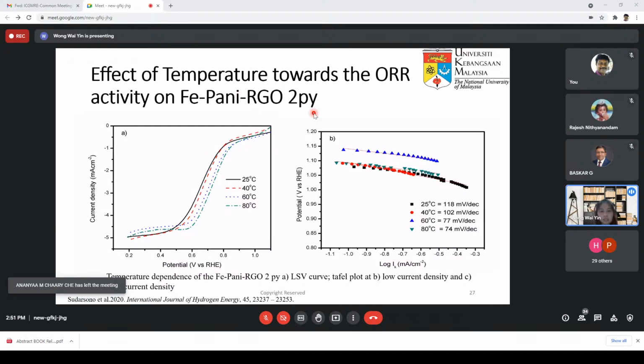And then we study the effect of temperature on the ORR activity of this selected, most active catalyst. You can see that we tested ORR with increasing cell temperature. Just for information, ORR is tested in a half cell. That means we only use a three-electrode cell system and only test its activity towards the oxygen reduction reaction, not in the single fuel cell yet.